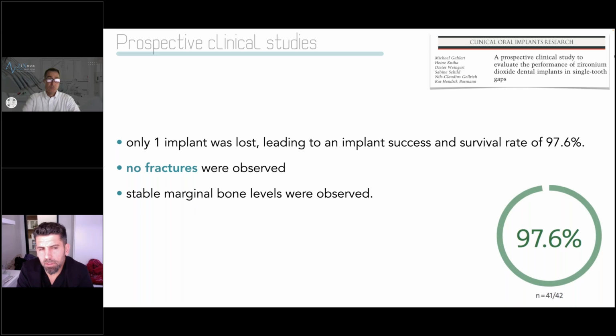Now let's look at some of the prospective clinical studies. These are from the Straumann company after they launched their one-piece implant. In this particular study, at 1 year follow-up, only one implant was lost, leading to an implant success and survival rate of 97.6%. So this is very comparable to our titanium counterparts. Very important, they did not observe any fractures on these implants, and they saw very stable marginal bone levels throughout.